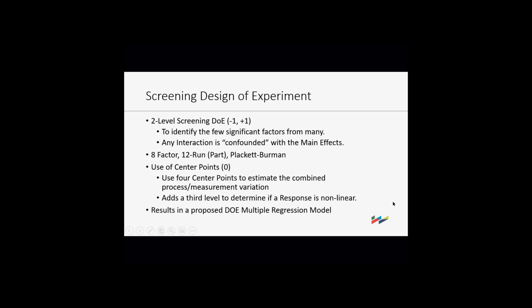Okay, so we start off with the screening design of experiment, and you usually do 2 levels, high and low. Because we talked about interactions, all those things are grouped together. So when you do a screening experiment, you cannot delineate between interactions and the main effects. They're all grouped together. With 8 factors, I can do it in 12 runs instead of 256. But you understand this is the first step, right? It could be an interaction that's causing it, or it could be the main factors that are driving this. But you're just trying to see which of the knobs will cause everything to jump, right? It's sensitive to that. And then I always put in center points because a lot of processes are not linear. They're curvilinear. So by throwing 4 points in the middle, I also get a sense of the variation in the settings.